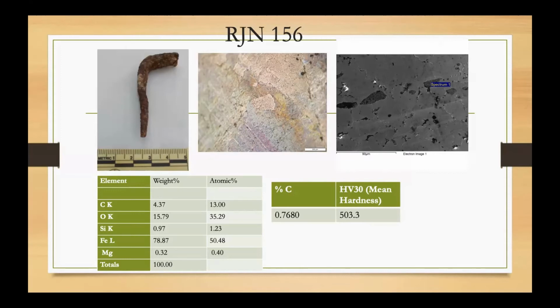So here you can see the carbon content goes up to about 0.7680%. And the iron content is 78.87, which is very high, which is also why this elemental study is important for us, because here we can understand that the smelting procedure was also pretty advanced, because otherwise maximizing your iron content over your silica content, which is maximum in your ore, is very difficult.